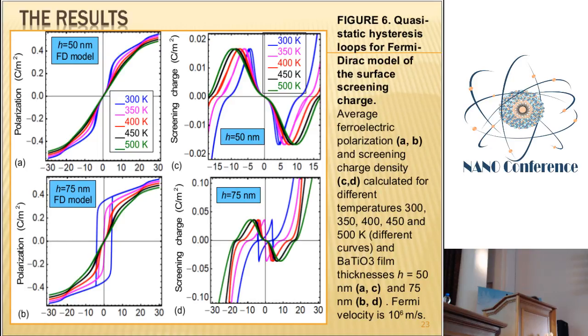When the film becomes a bit thicker, for example 75 nanometers, we see a single hysteresis loop at room temperature and a double hysteresis loop at higher temperature, and only then the loop disappears. And the origin of these double loops is not related with the order of the phase transition in the ferroelectric, as typically is expected, since ferroelectrics with a first-order phase transition can have double loops. No, since the hysteresis takes place in an interval of at least 100 kelvins, it is related with the nonlinear interaction between the ferroelectric dipoles and screening 2D carriers at the surface. The same can be seen from the screening charge, nonlinear maxima, and their eventual disappearance with temperature increase.